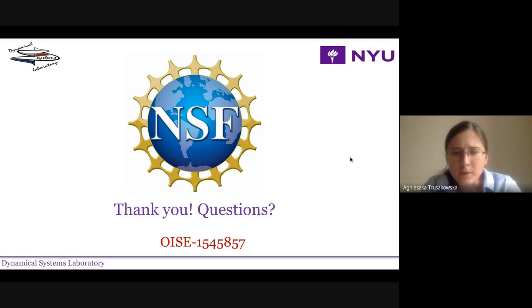And the ensembles I used were basically for the equilibration. I use a combination of NVT and NPT ensembles. And I follow a procedure that was published for a bulk Nafion membrane, and it includes annealing and also a final longer NPT simulation to relax the volume.